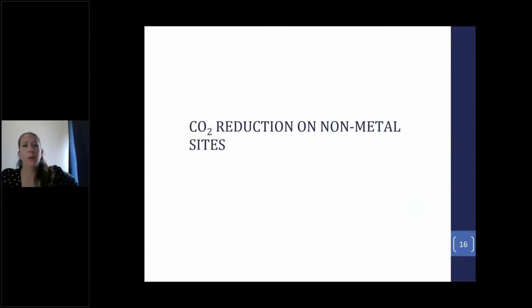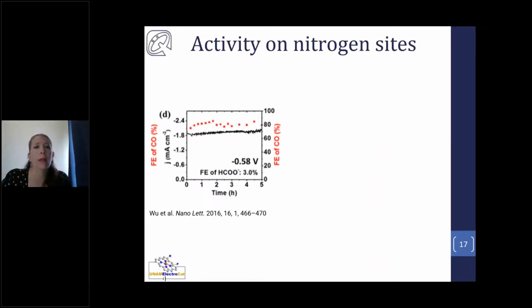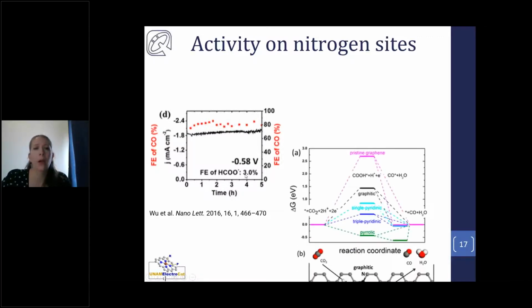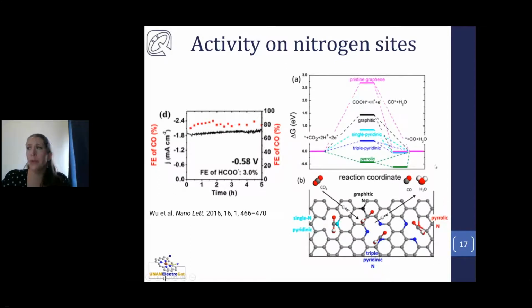This is something I want to briefly mention because we saw something we were not expecting. We knew for a while that nitrogen-doped carbon is also active and selective for CO2 reduction. I'm just showing you one example where they show a high selectivity towards CO on a nitrogen-doped carbon. They also supported their observation with DFT, density functional theory calculations, and they see that this triple pyridinic site is most likely the active site for CO2 reduction. Whereas the graphitic site seems not to be active, or would have a much larger overpotential for CO2 reduction.